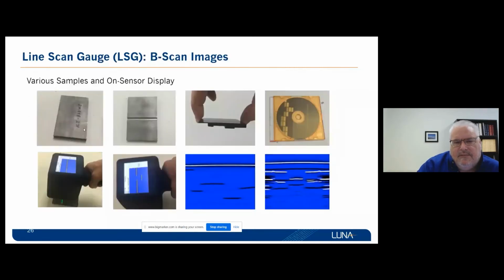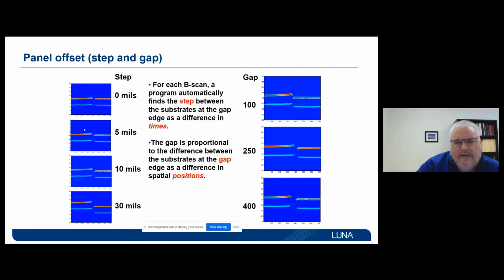Here I'm going to show some examples of B-scan type measurements where you are scanning the terahertz waveform over a coating or a surface, and you want to measure, say, the step and gap or the location of defects underneath the coating. So the upper right is a step and gap test area, and the lower right-hand side shows three-dimensional forms where you can see the cross section and B-scan images.